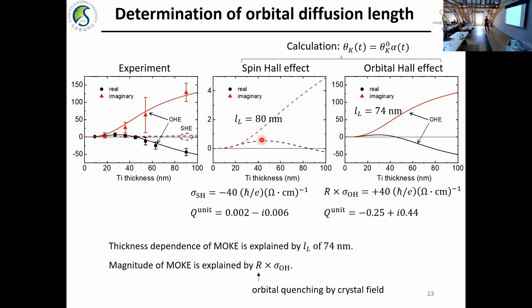In the case of the real part, you see it is quite different. The reason is that for the magneto-optical constant for spin, the imaginary part is about three times larger than the real part. While for the orbital magnetization, they are more comparable. As a result, you have not only a different magnitude but also a different shape compared to the simple spin Hall effect.